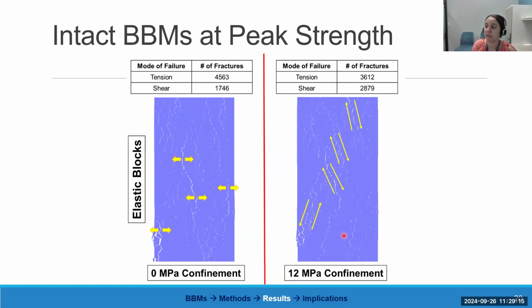I also want to note that I'm showing the models here right on the cusp of failure. It's right at peak strength. So right as the model is failing, if we were to continue the simulation all the way to residual strength, you'd eventually see these shear bands coalesce into a large shear band that goes from one side of the specimen to the other, which is what I'm sure you all are used to in the lab.